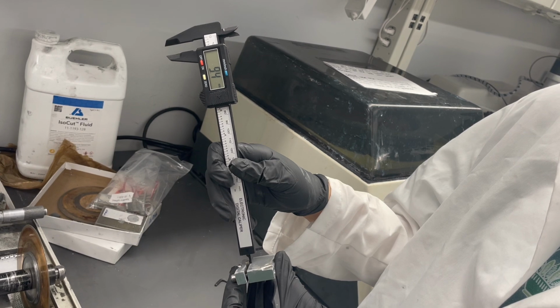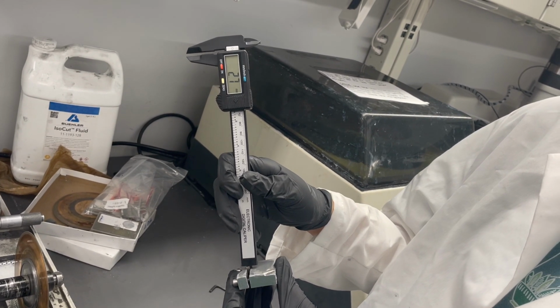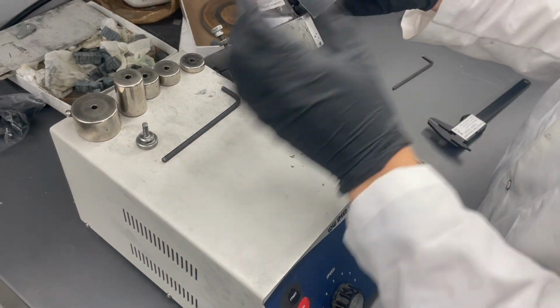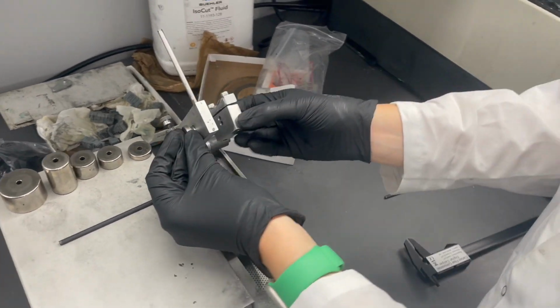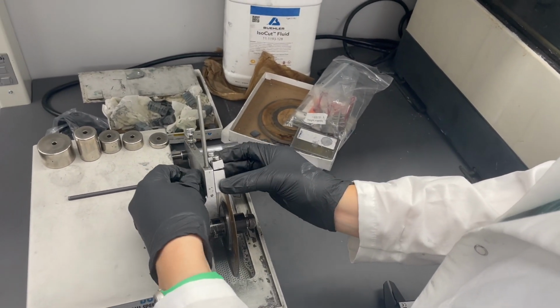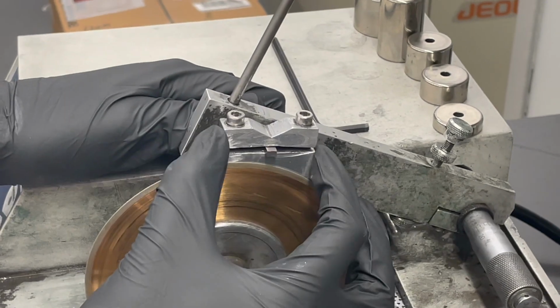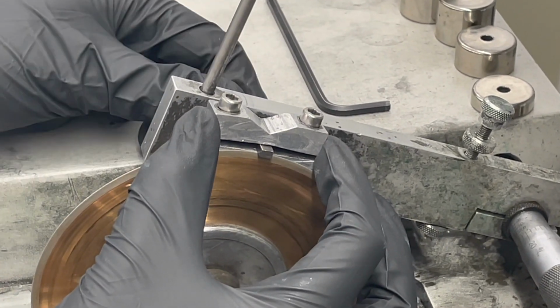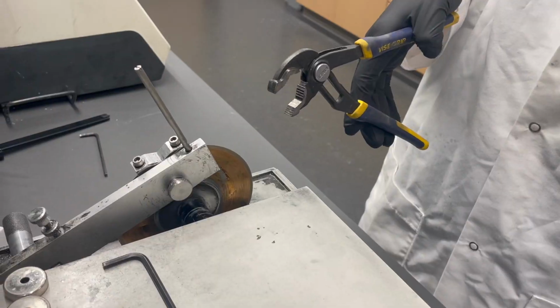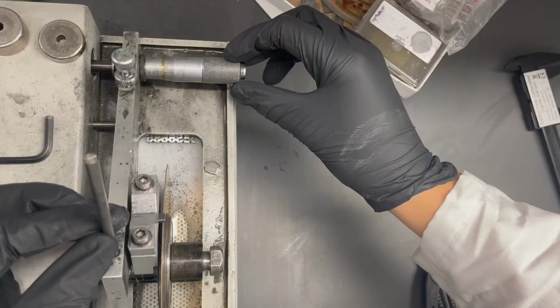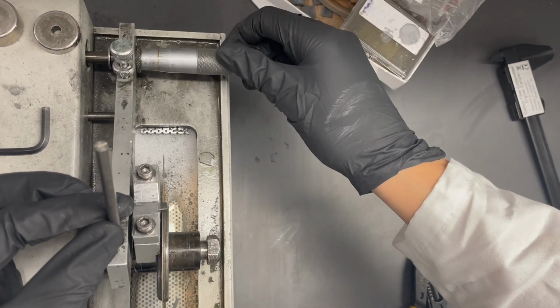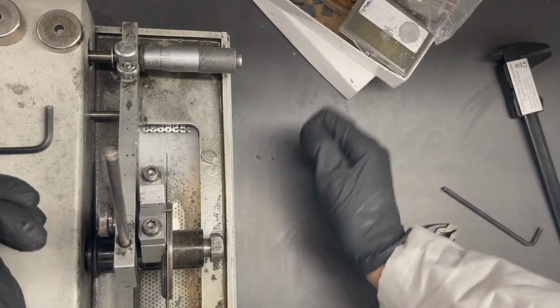Use the calipers again to measure the sample in the sample holder. Now use the screw to attach the sample holder to the saw. Be sure the center of the sample is contacting the saw blade. Use the pliers to tighten the screw and use the fine-tune knob to fit your desired dimensions.